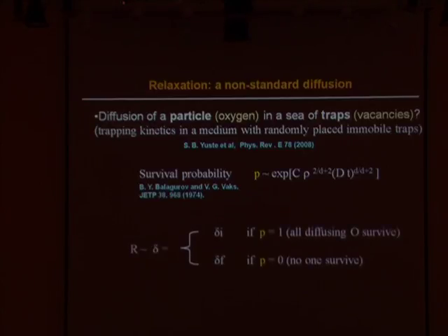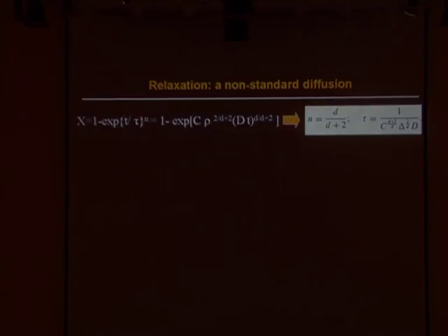Making simple mathematics, we can associate the resistance that we are measuring, which is in principle proportional to the density of vacancies, and then you can express the relative change of the resistance as you obtain. This is the X function that we use to plot our data, and this X function will be proportional to 1 minus P.